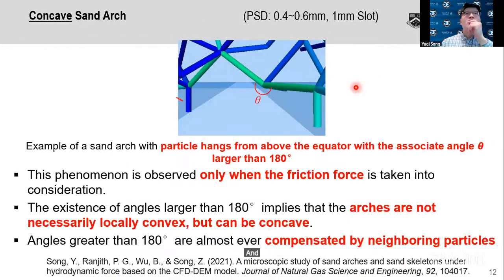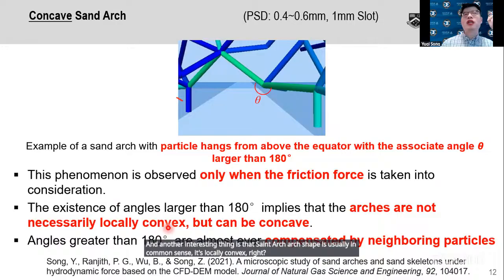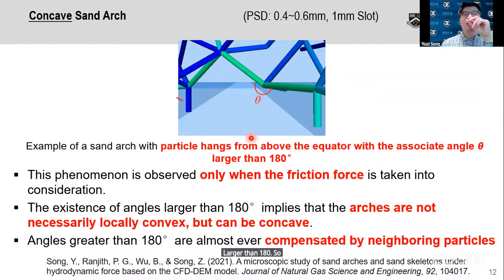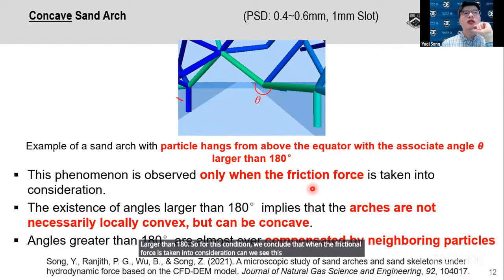Another interesting thing is that the sand arch shape is usually, in common sense, locally convex, right? But in our sand arch, we found a concave sand arch, where theta is larger than 180 degrees. We see that a particle comes from above the equator with an angle larger than 180. We conclude that this phenomenon can be seen when the frictional force is taken into consideration. It might be unstable, right? But the instability can be compensated by its neighboring particles.